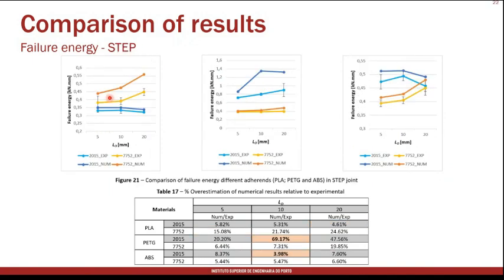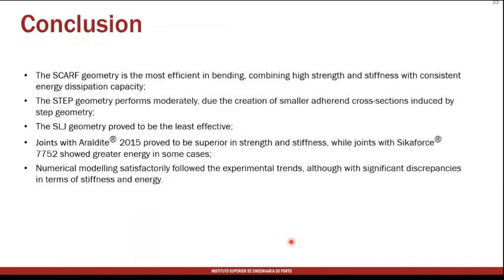For the step joints, and because of the fact that we have almost always failure in the adherend, there were no significant differences, but once again, we have a good correlation. Here there was some condition that we had clearly some problems that we need to look at, but typically we have a good consistency between the values. In terms of conditions, we compared different joint geometries, we compared different adherends and different adhesives.